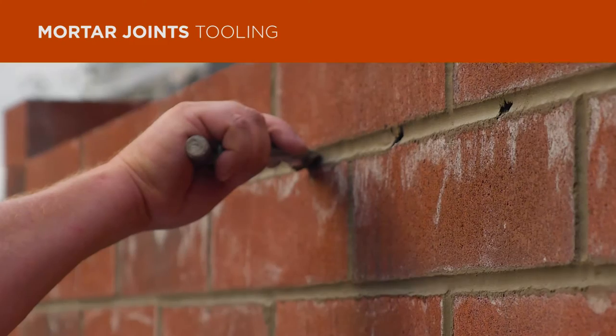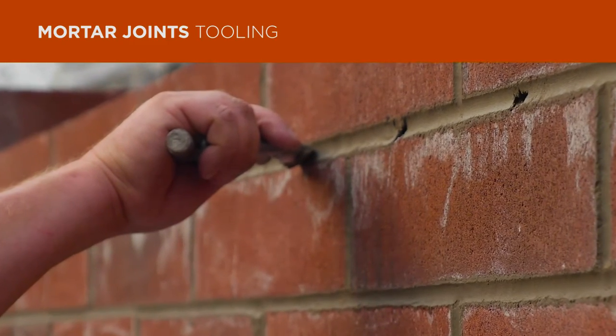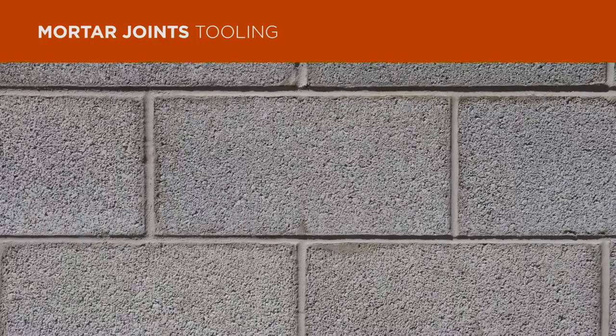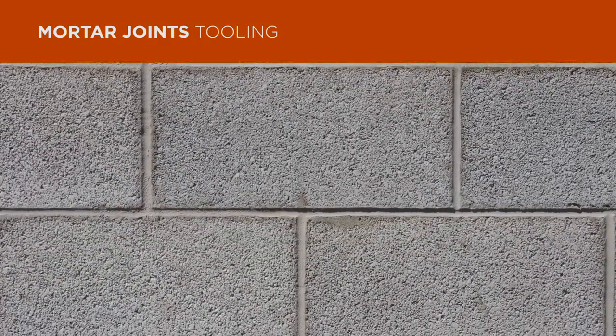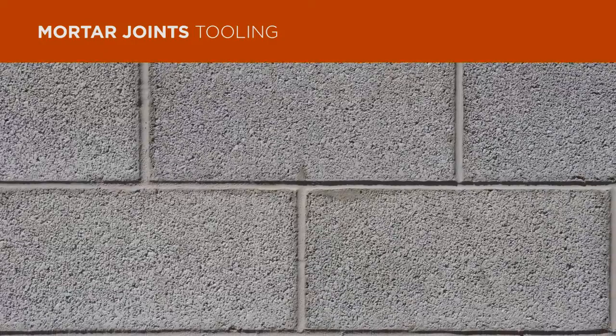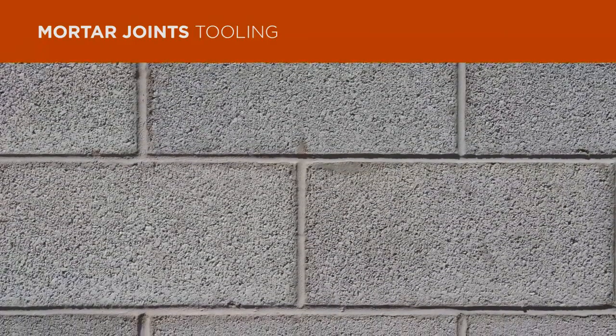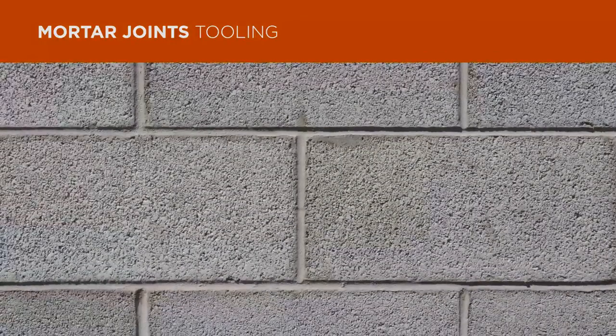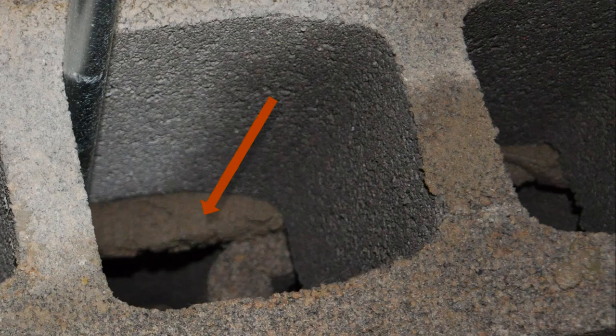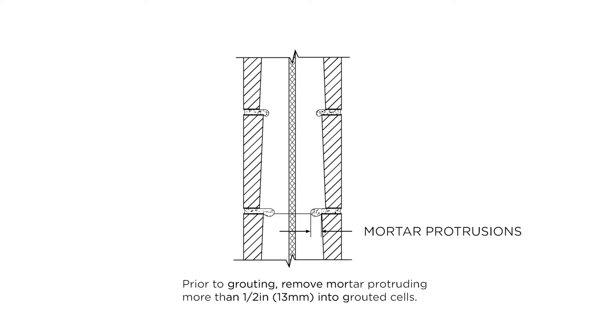The code requires that all joints be tooled with a concave joiner when mortar is thumbprint hard, when not required otherwise. Thus, when not indicated otherwise, strike the joints with a concave joiner. This applies to backup assemblies and other locations where the finished surface will not be exposed. The code requires that any mortar protrusions into hollow cells over 1/2 of an inch be removed if the cell is to be grouted. Grout placement requirements from building code assume that cells to be grouted are reasonably clear of obstructions. Removal of mortar protrusions over 1/2 of an inch helps to prevent voids in the grouted cells.